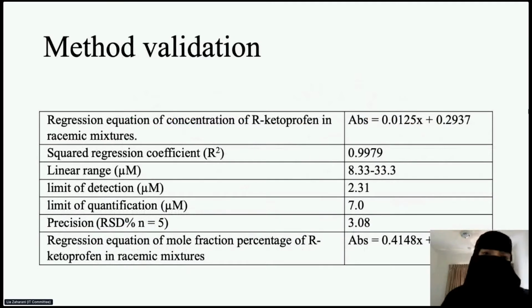In the method validation, I got a nice result, as you can see in this table. The linear range is from 8.33 micromolar to 33.3 micromolar. The limit of detection is 2.31, and the limit of quantification is 7. I repeated the experiment 5 times, and this is the RSD of my two previous relationships.